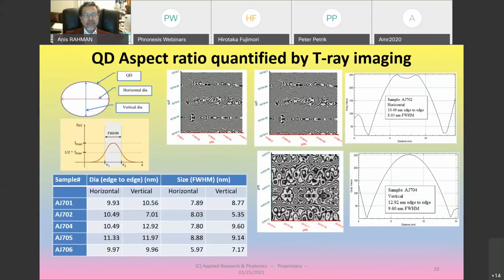So with the particle size determined, we found that some particles have some aspect ratio. Some of them are spherical. So we had a chance to then quantify those factors. And we saw that particle edge to edge is 10.49 nanometer. Here, this table shows horizontal and vertical size distribution from edge to edge, and on this table is full width at half maximum. A lot of the time particles are measured that way because of the edge effect. So the edge to edge matches better with the TEM data, but also we can see that there is an aspect ratio. It's not particularly spherical particles.